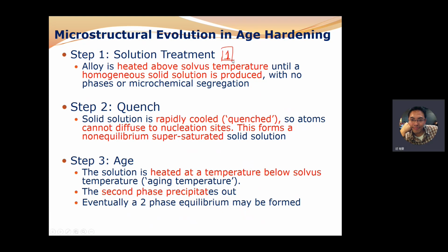In step 2, quench. The solid solution is rapidly cooled, so atoms cannot diffuse to nucleation sites. This forms a non-equilibrium supersaturated solid solution. So this is point 2.